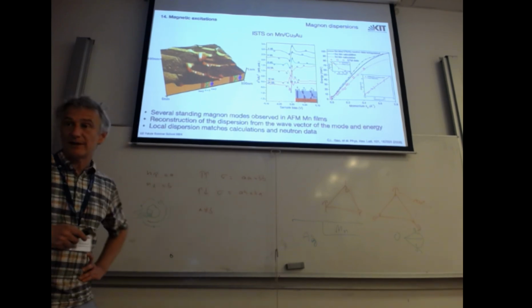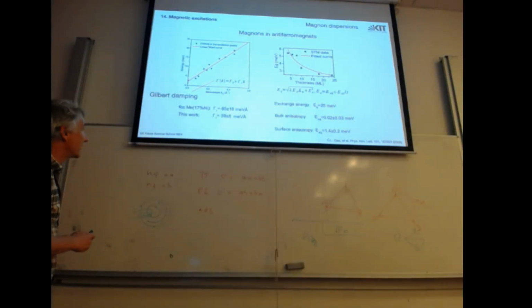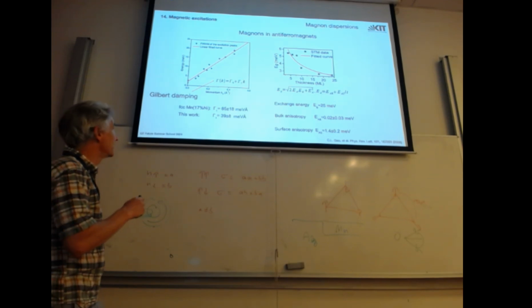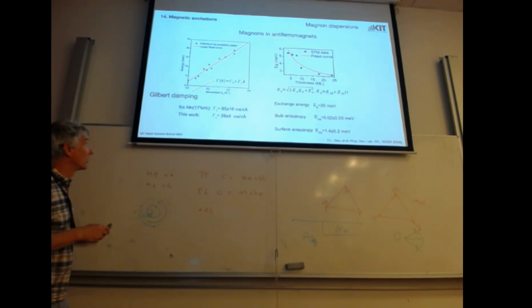And this is the lifetime of the magnon. And the lifetime of the magnon is different from the electronic states. It depends on energy, and this is called Gilbert damping. So the damping factor is some intrinsic damping plus an energy dependent damping. It's linear for antiferromagnets and ferromagnets. And this is our fit. We get a relatively good agreement.